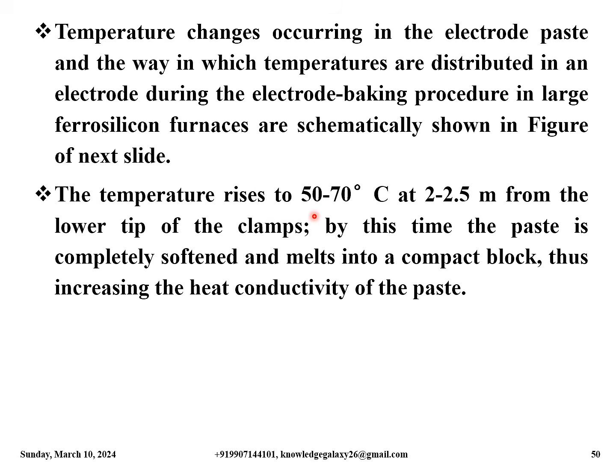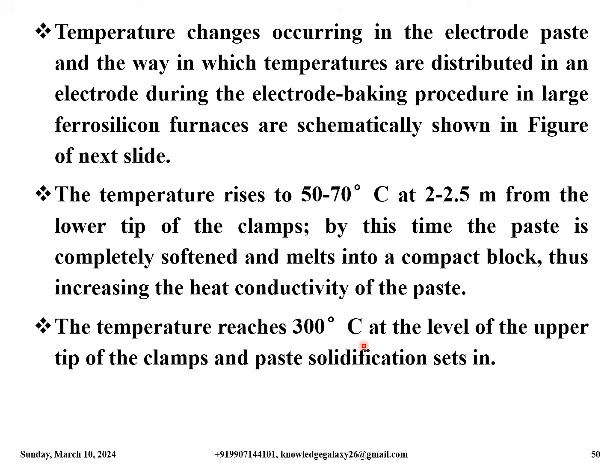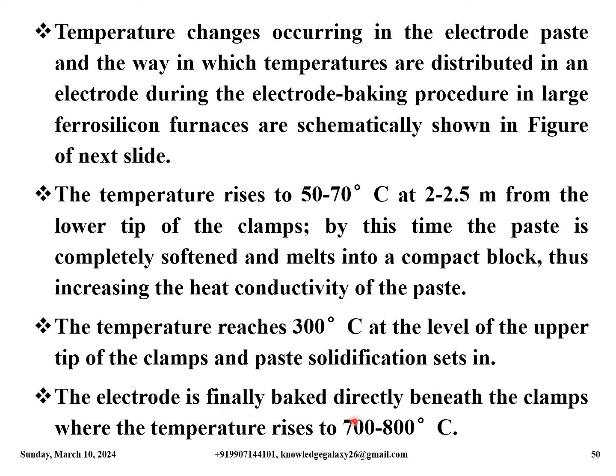The temperature rises to 50 to 70 degrees Celsius at 2 to 2.5 meters from the lower tip of the contact clamps. By this time, the paste is completely softened and melts into a compact block, thus increasing the heat conductivity of the paste. The temperature reaches 300 degrees Celsius at the level of the upper tip of the contact clamps and paste solidification sets in. The electrode is finally baked directly beneath the clamps where the temperature rises to 700 to 800 degrees